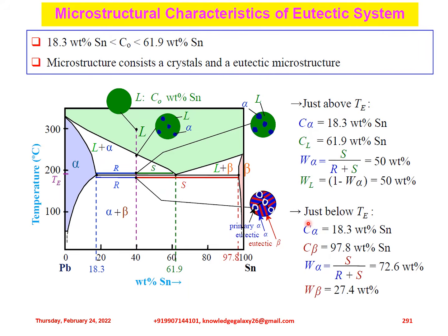And now let us consider just below TE, this portion just below TE. What happens? C alpha is 18.3 weight percent tin, C beta is equal to 97.8 weight percent tin, and weight of alpha is equal to S divided by R plus S, which is 72.6 weight percent. Here the picture is clearly depicted with different colors to differentiate them, and weight of beta comes to 100 minus 72.6, which is 27.4 weight percent. You can pause the video and observe this picture in more detail. What are all the phases present and their proportions?